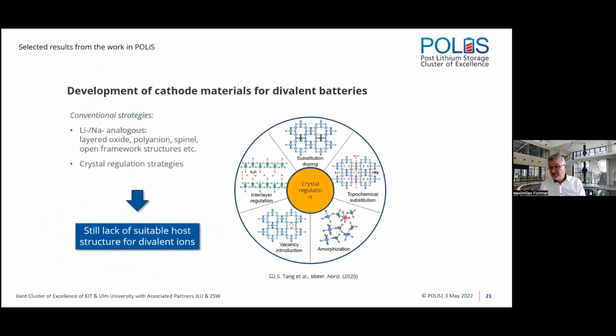And if you look at what was done in the literature in the field, most people were actually pursuing conventional strategies, in that they tried to test analogs of lithium and sodium systems, like layered oxides, polyanions, spinel structures, open framework structures, etc., and wanted to solve the problem by crystal regulation strategies. But as an outcome, we are still looking for good insertion type materials in this field. So there's still a lack of suitable host structures for divalent ions.